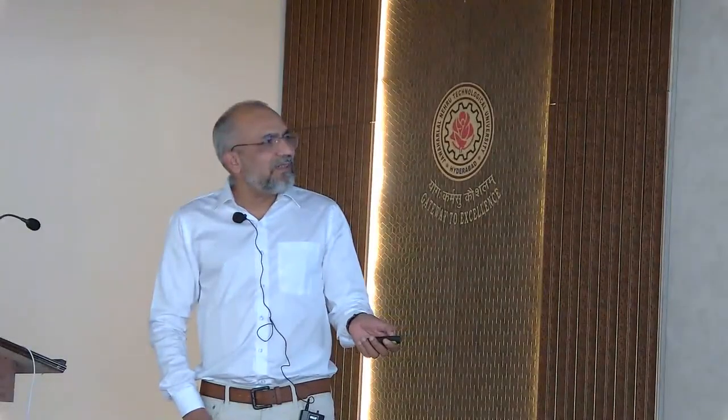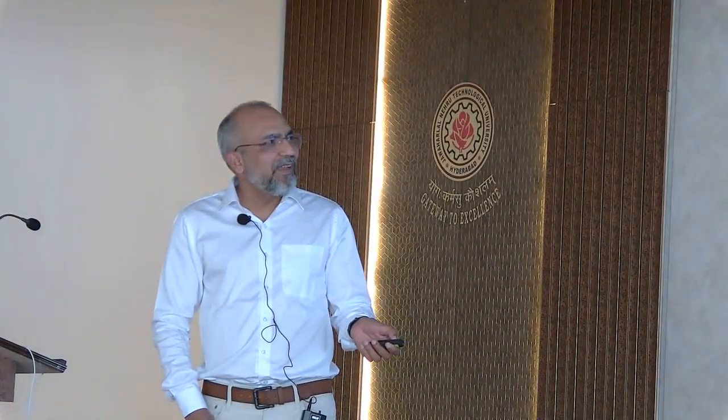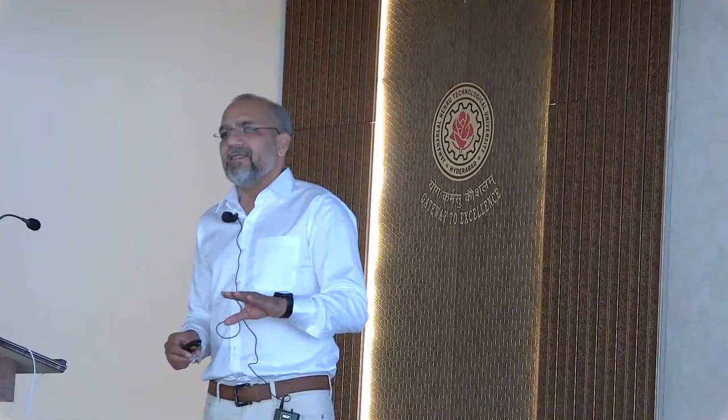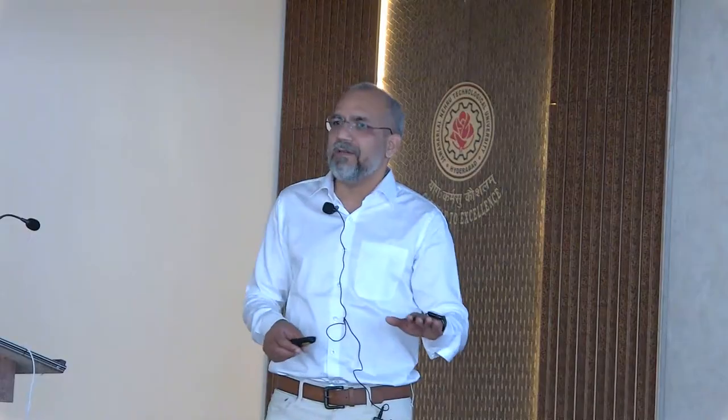So in this one, that's a tube here, and in the tube we should have these 2 blocks, ceramic blocks. And when we were setting up the CVD device, I took them out. And every time I was running the experiment, there was no graphene on the copper. One day, just to see, I flipped the copper. On the bottom, there was a lot of graphene, but on the top, no graphene.